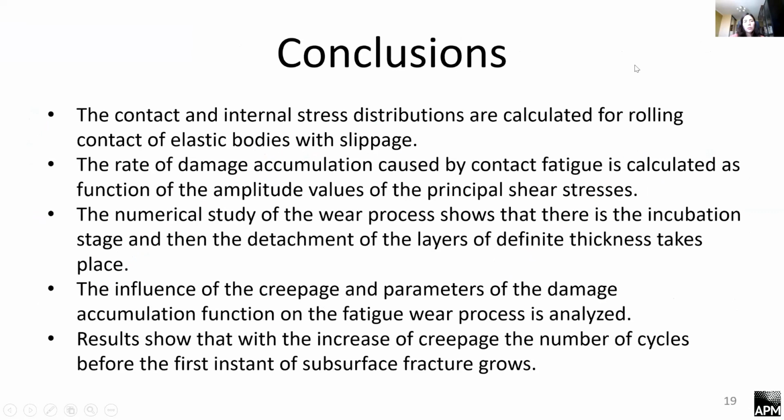So in this research, we calculate the contact and internal stress distributions for elastic bodies in rolling contact. And with these internal stress distributions, we calculate the damage accumulation rate caused by contact fatigue. And here, for the damage function, we use amplitude values of principal shear stresses. The numerical study of the wear process shows that there is an incubation stage, and after this incubation stage, there is a detachment of the layers of different thickness. Also, we show the influence of creepage and parameters of damage function on the fatigue wear process. Thank you for your attention.